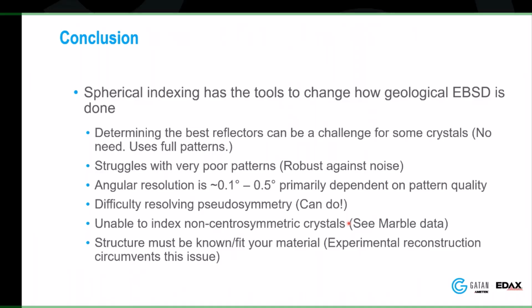I don't have to worry too much about poor patterns. Again, I always want to start with the best that I have, but I'm robust against noise. If I do have some noise, as long as there is information in there, we can do a pretty good job of pulling the information out. So if I see material that's deformed, or sample prep was tricky, we're really bending the learning curve here to allow EBSD, on the geological side, to be more easily used by everybody.